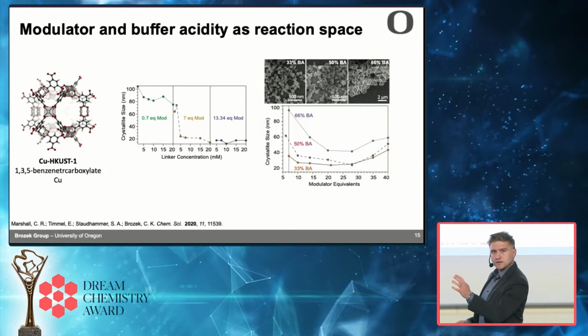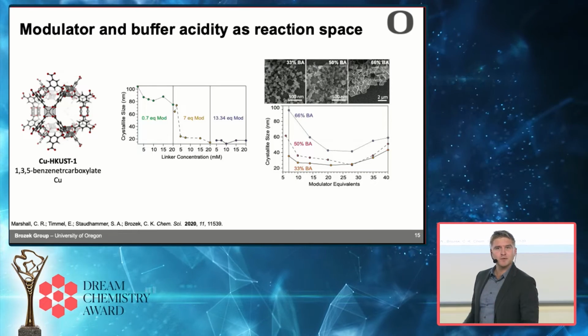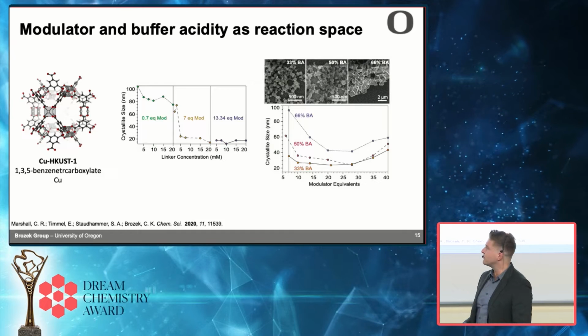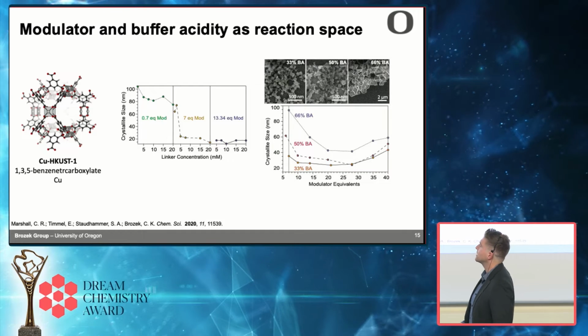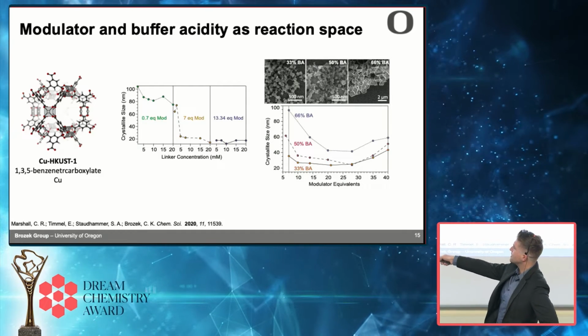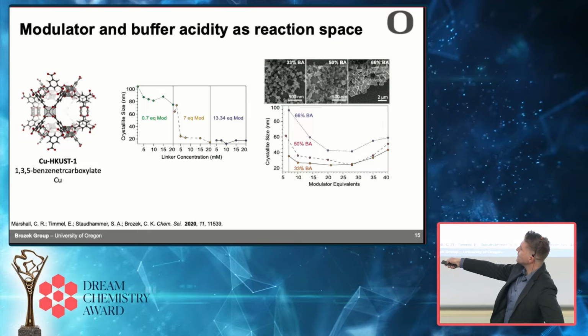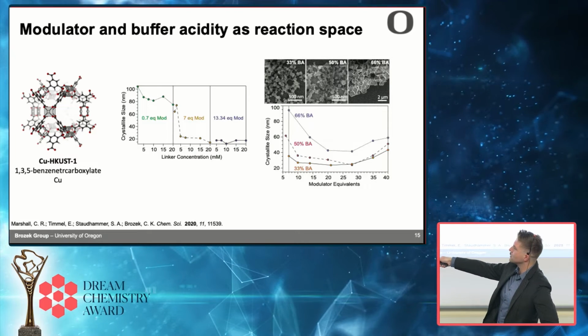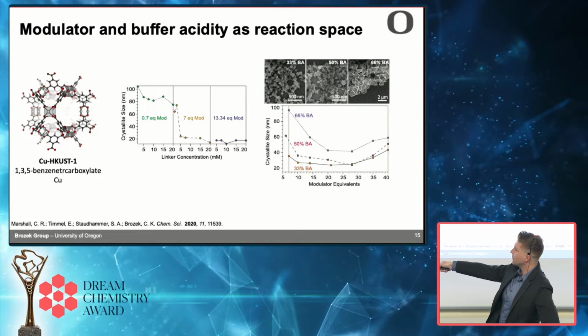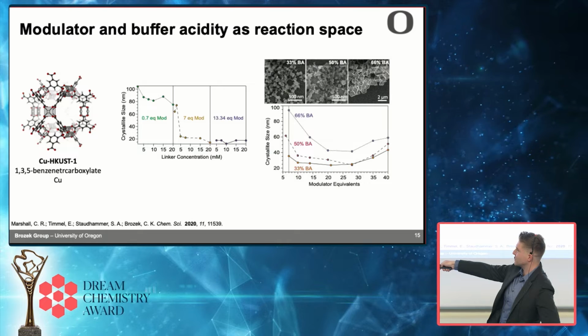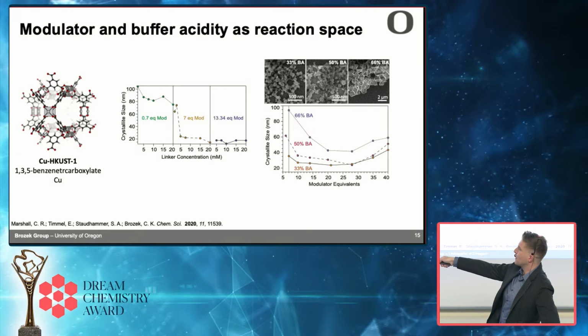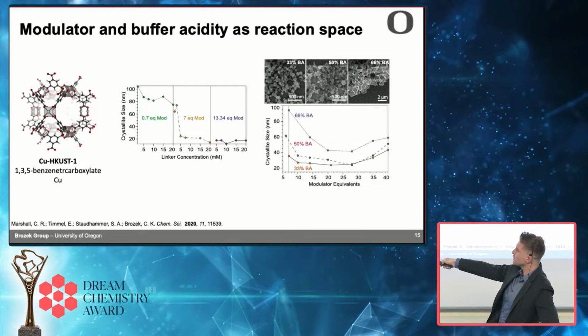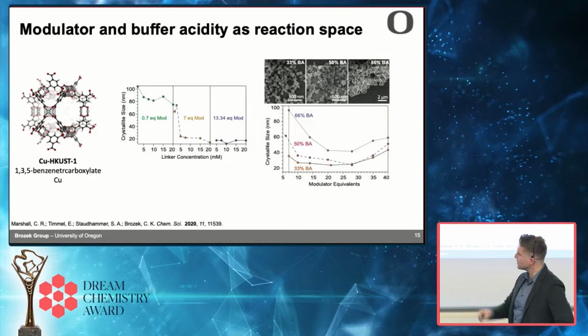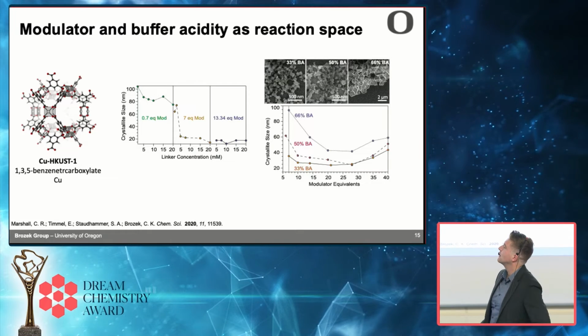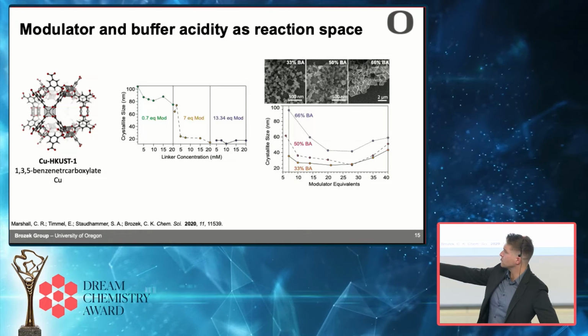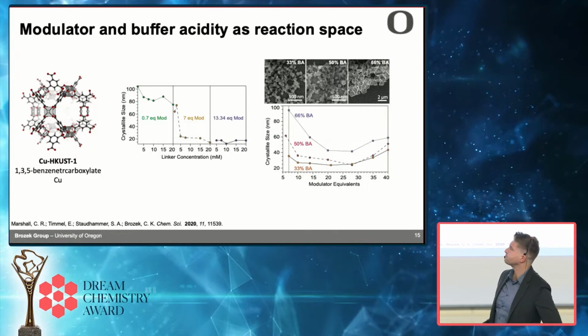And we said, well, let's look at all the different synthetic parameters that people typically explore and investigate the impact on particle size. And so these are 3 separate sets of experiments where the only difference is how much modulator we use. So in all these experiments, we're increasing the concentration of the reaction. But the difference between these is how much modulator. And we see that, okay, concentration matters. It kind of pushes the sizes down. But what seems to matter much more is simply how much modulator you used.